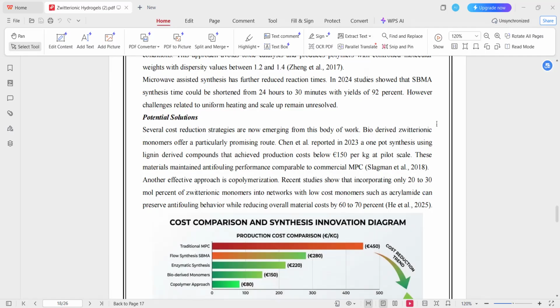Several practical solutions to deal with this challenge are also emerging. One particularly promising strategy is to use bio-derived zwitterionic monomers. In 2023, Chen and colleagues reported a one-pot synthesis using lignin-derived compounds that reduce production cost to below 150 euros per kilogram, while maintaining anti-fouling performance comparable to the commercial MPC.